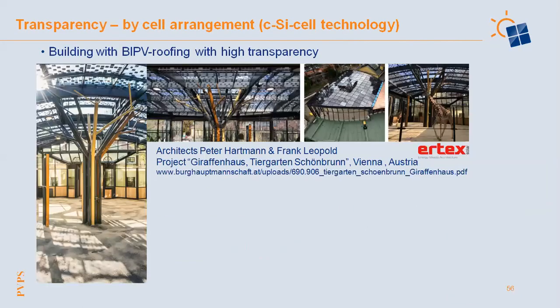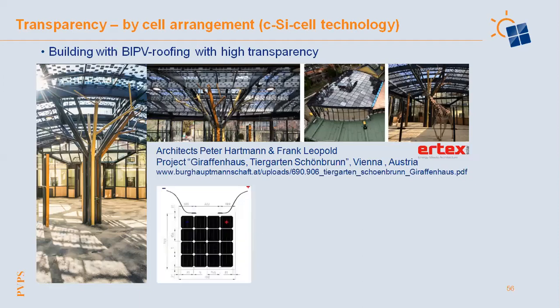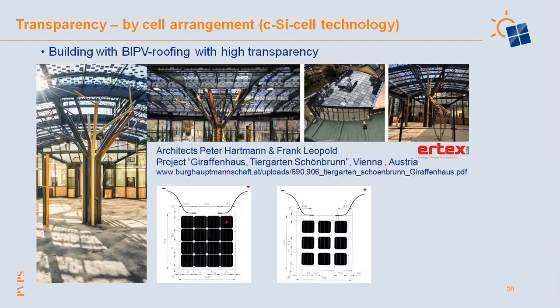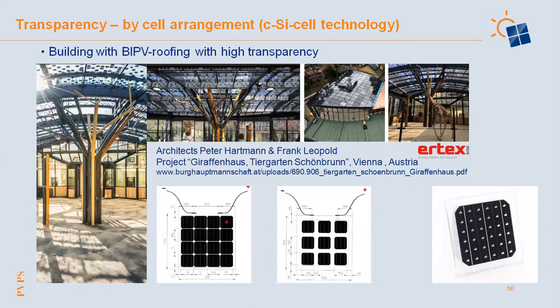Transparency with the standard crystalline silicon technology can only be achieved by a special cell arrangement. If you increase the distance between the silicon cells, because the silicon, of course, is not transmittive at all, then you can have a shading effect plus good lighting in the room beneath. Or you use laser cutting and make special holes in your silicon cells, but it's possible to control the light entering your house by using this technology.